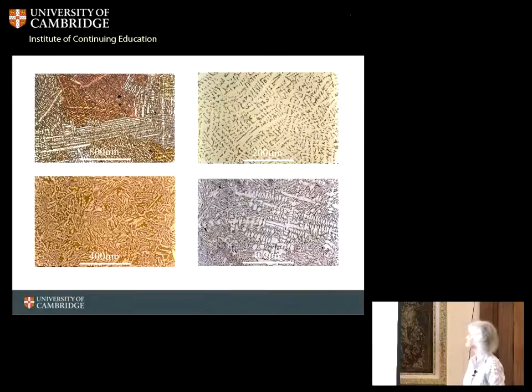Let's up the zinc content again. So these are the first two images we looked at. These two have even more zinc in. They've got about 40% zinc, and that's beginning to be at the limit of what we see commercially. We can see the same kind of thing. We've got a mixture of two different kinds of structures, and in lots of places it's beginning to break up completely. We're now seeing things that look more like platelets. These two, and particularly the one at bottom left, have what we call a Widmanstätten structure.